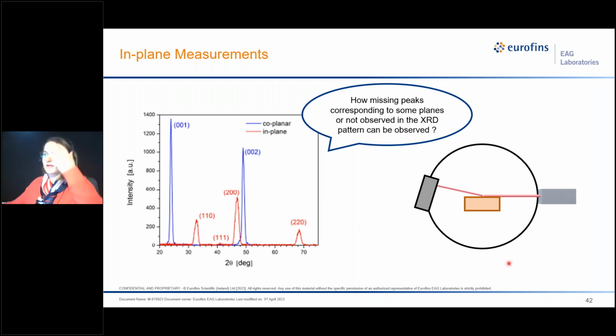Okay. So we also got some questions like, how can missing peaks corresponding to some planes not observed in an XRD pattern be observed? One method of doing that is what's called in-plane measurements. Instead of doing our typical collection perpendicular to the plane of the surface, we want to collect the planes that are now facing this way. And so we swing the X-rays and the detector in the plane of the material.